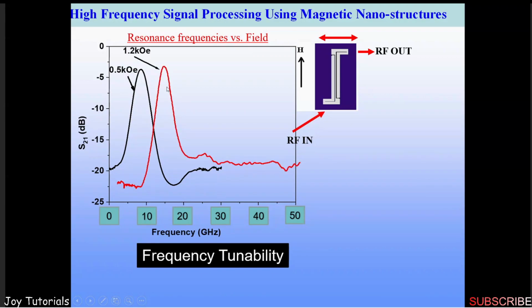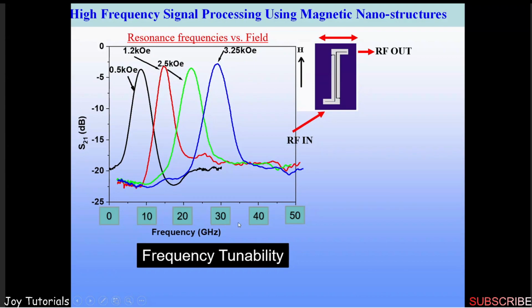Then after designing this, what we saw here is, for example, a nanowire-based band pass filter. There are two antennas, at say 1 micron. We designed the antennas 2 micron to 10 micron apart from one signal line to another, depending upon what kind of operation we want. But you can see here, there is a very small field of 500 gauss, and the operating frequency is almost close to 8 gigahertz. It's a high frequency, the microwave range of the X band. If you tune the field, the same device can go to a higher frequency, like 15 gigahertz, with a little higher field of 1.2 kilo-oersted. The same device can operate at 2.5 kilo-oersted going towards 20 gigahertz and beyond. If we put a little higher field, it can go even up to 30 gigahertz and so on.